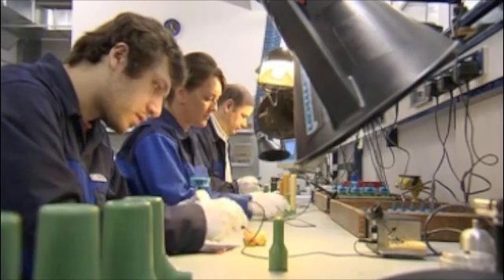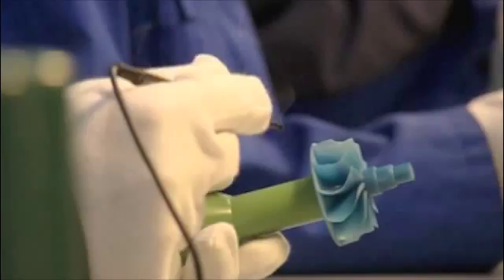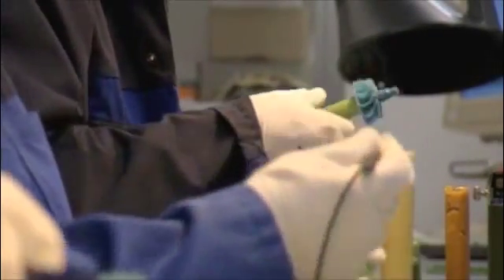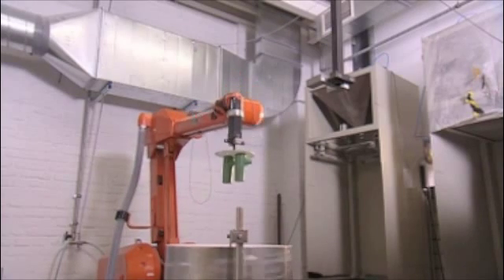Casting gamma-titanium aluminide presents a considerable challenge in terms of process technology. A high melt temperature, the importance of avoiding inclusions of oxygen when melting and casting, coupled with only a small melt interval, all combine to make the process especially difficult to master.